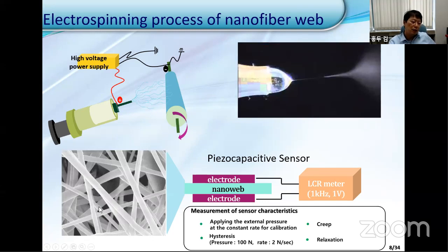In this case, as you see here, there is a lot of void. And if you choose a proper polymer material, you can change the dielectric constant as you press it. That's why we try to use a nanoweb instead of films, so that the sensitivity increases very dramatically. For the piezocapacitive sensor, we just attach electrodes on the top and bottom, and then we can measure the capacitance.